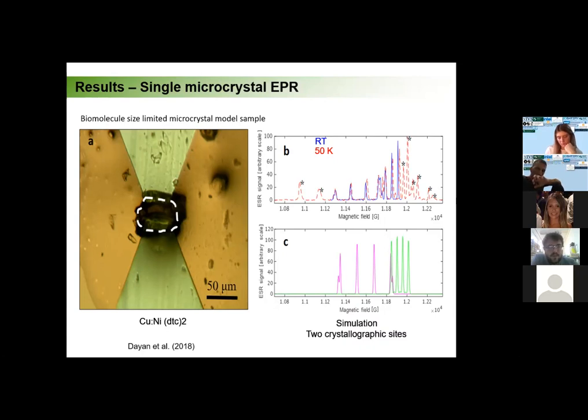So we took this biomolecule model, which is composed of copper and nickel, and we were able to measure its EPR spectrum. Here I show you, we measured it at room temperature in blue and at 50 Kelvin in red. And we are comparing it to the simulations, and we see it's a good fit. What we see in the red, in the asterisk, is some impurities that come from our substrate, the dielectric lanthanum oxide.